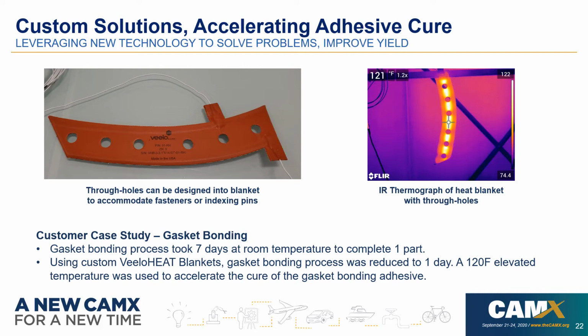So we did a case study with this customer on gasket bonding. Their process is a room temp process. It took 7 days to complete one part, and then using an array of these custom VeeloHEAT blankets, we were able to demonstrate the same gasket bonding strength in only 1 day. We achieved this by using a 120-degree Fahrenheit elevated temperature with our blanket and a custom controller, and this was used to accelerate just the curing process of this room temp adhesive.